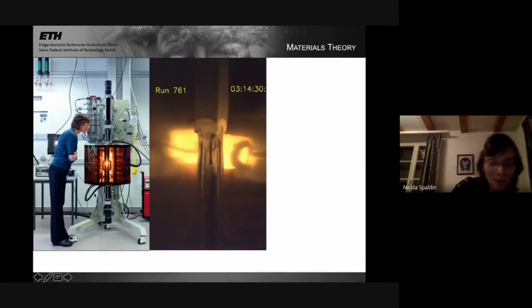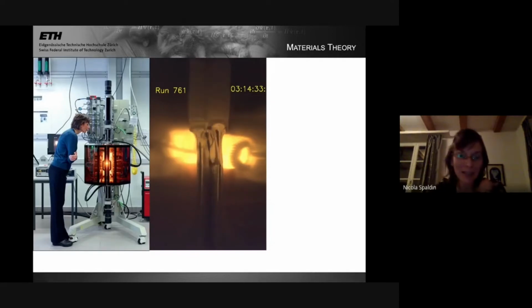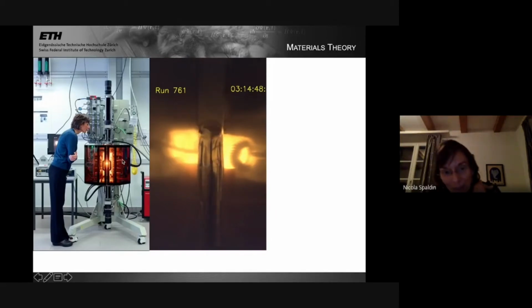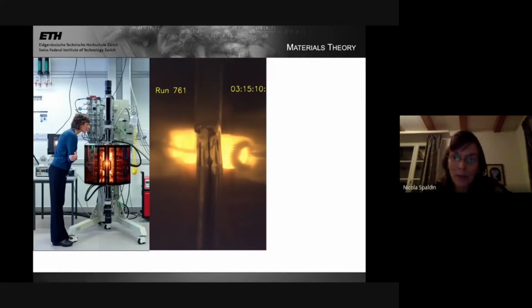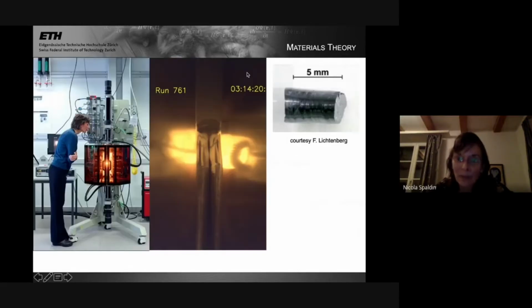So I have to show you this picture because I'm trained as an electronic structure theorist. And when I moved to the ETH, I set up an oxide single crystal growth lab. So I'm extremely proud of this. I'm very excited. This is our furnace. This is a video of a crystal of yttrium manganite growing in the furnace. The furnace basically has mirrors that concentrate a light beam and make the sample extremely hot. And we slowly pull the sample through this floating zone, this molten zone where it's melted by the heat from the light beam, and it crystallizes into this beautiful single crystal on the other side of the very hot zone. The crystals can be quite large, so we can study them with neutrons. And this one was grown by my senior scientist, Frank Lichtenberg.